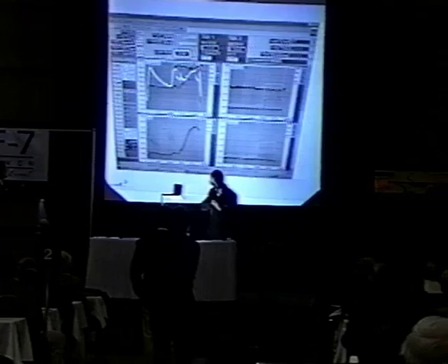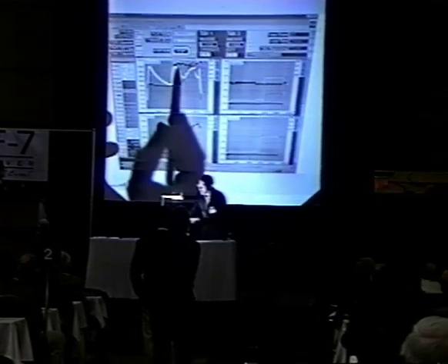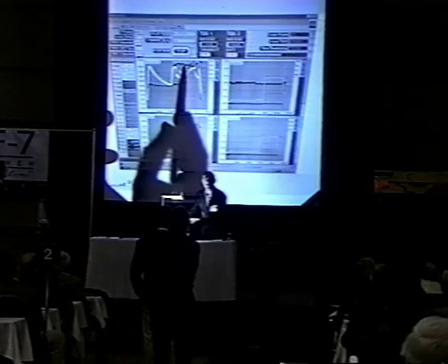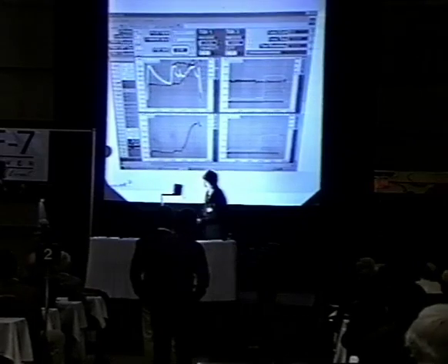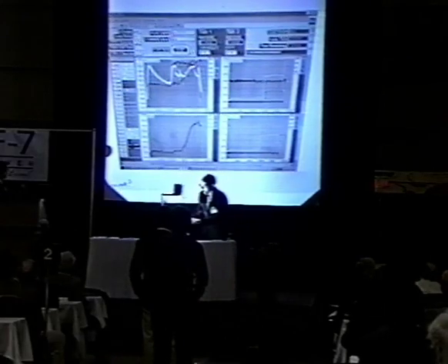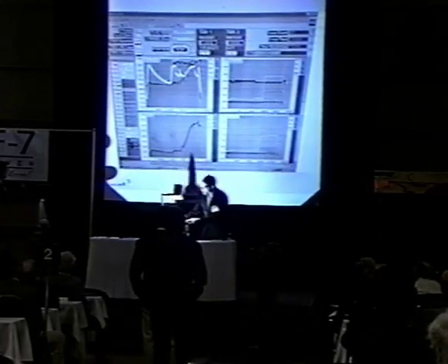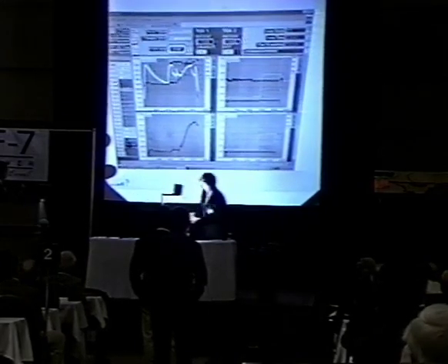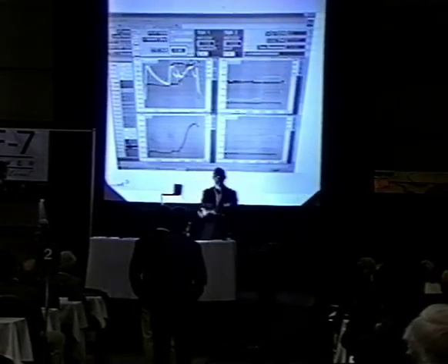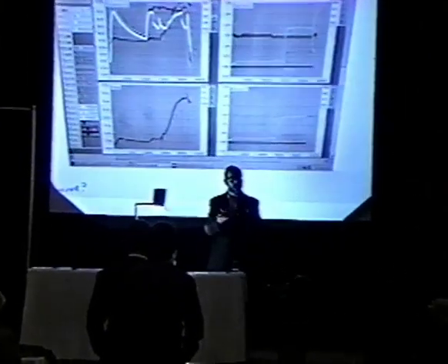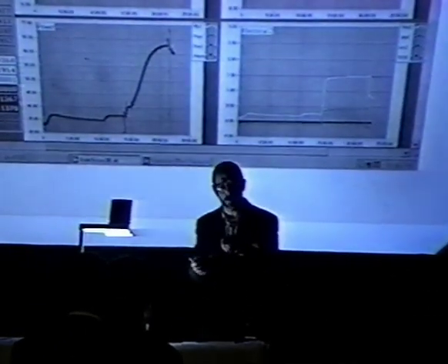If you take a look, what I'm plotting right here is essentially the cell. The black one is the bottom cell temperature, and the white plot is the cell temperature at the top. Now, this was a system that basically made no heat. I heated it up, just let it cool back down, heated it up again. There's no thermal power coming out of the system. And up until this point right here, there was no current running through it. But notice, before the current is turned on, this was a small 250 milliliter beaker, and it was evaporating at the top. So I just went ahead and put in some distilled, deionized water, cold, room temperature.